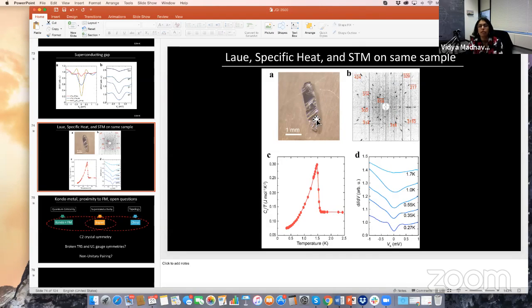For uranium ditelluride, it's amazing. Nick Butch and Sheng Ran made very beautiful single crystals, and let me just show you what I mean. We did Laue on these single crystals, and for these giant single crystals, the whole thing is in one phase. These measurements are all done on this particular crystal. You can see a very beautiful specific heat jump, and it happens around 1.6 Kelvin. In fact, the superconducting gap measured by STM also disappears around 1.6 Kelvin.